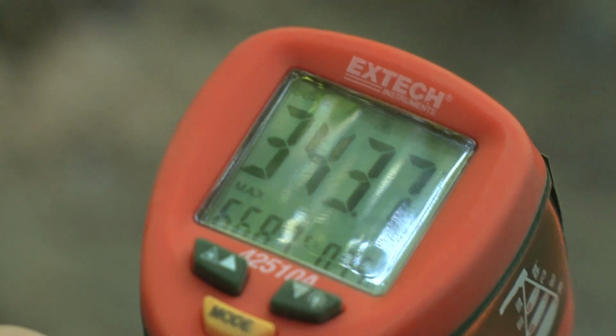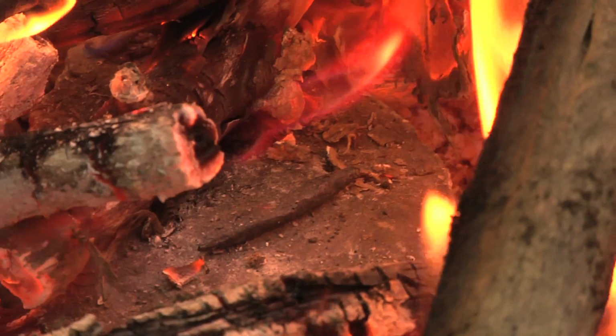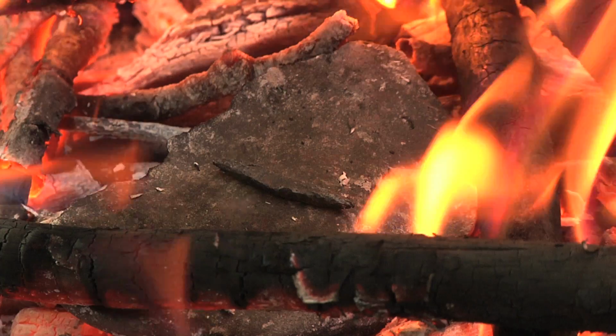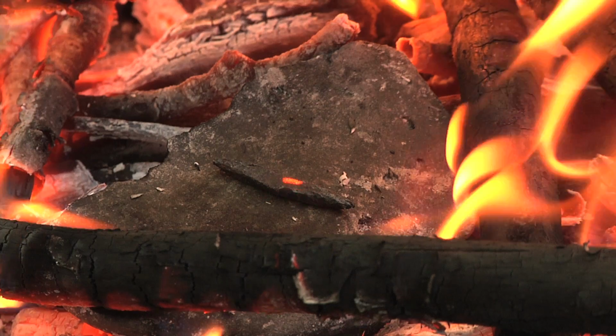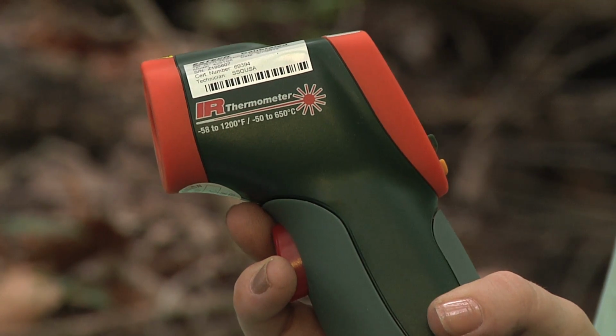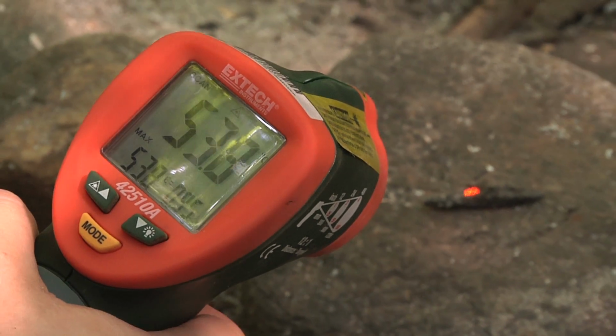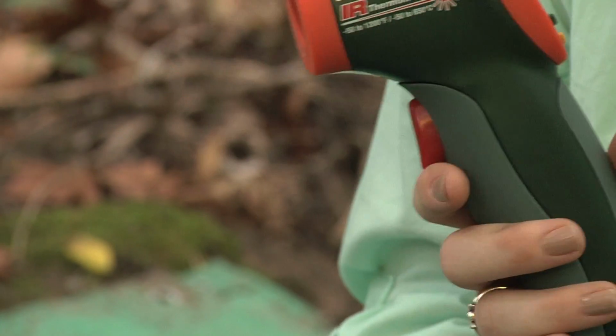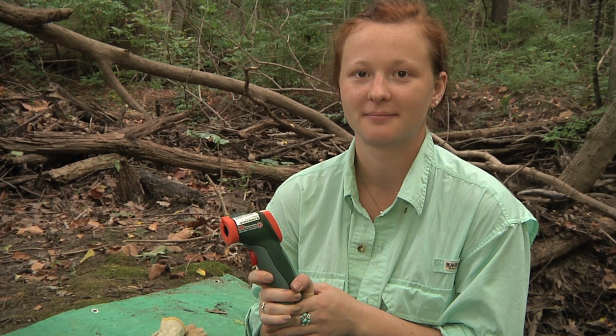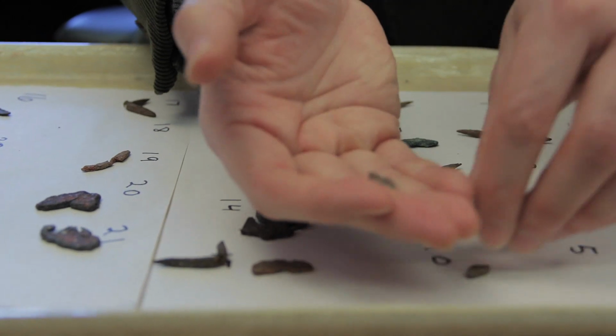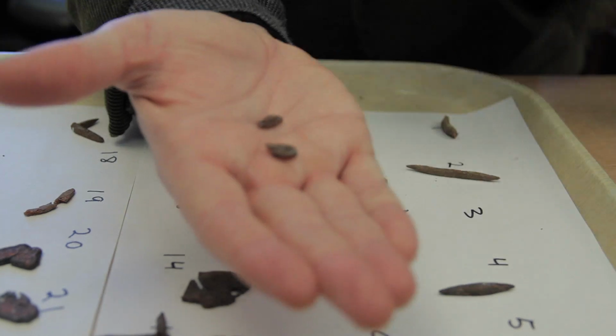We want a dull red, which indicates what we've measured to be around 700 degrees. That's the color that has been found to indicate a good anneal and a good annealing temperature. If it becomes cherry red, that's too hot, but if there's no red color at all, then that's not hot enough. The prehistoric people wouldn't have had temperature reading devices like we do here, so they would have used the color indicator method. It would appear that pretty much everywhere native copper was used in the ancient world, annealing was part of this technology.